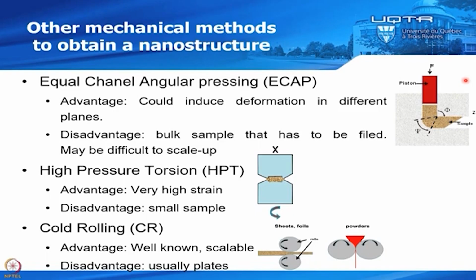So you could get a highly strained material, and also you could get nanocrystalline structure that way. The advantage is that you could repeat that many times, and depending on how you push back the sample, if you rotate it 90 degree or 180 degree, you could induce deformation in different plane. So this is interesting because according to the crystal structure of your material, you could say, well, I would like to induce deformation mainly in that plane and not in that other plane. So from a fundamental point of view, this is quite interesting.